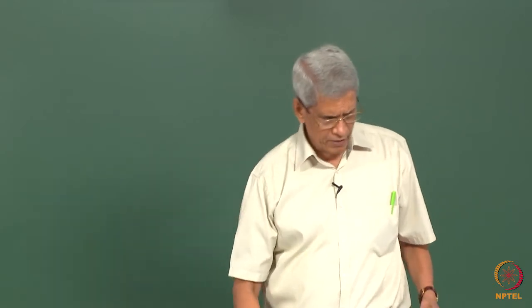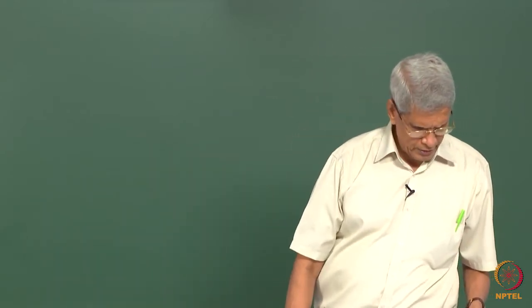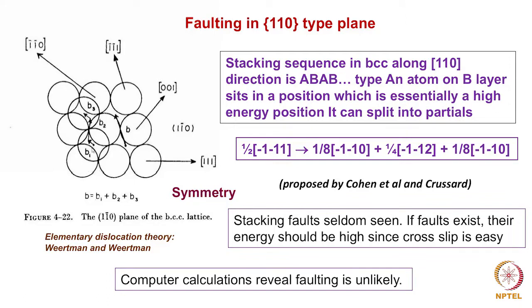Here essentially what we are trying to do is look at how the atom which is sitting on the top should be moved to an identical position by a movement of a/2 111 dislocation. So the atom sitting on the top comes to a slightly low energy position. From there it shifts to another low energy position, from there it shifts to a higher energy position. That is how it can reach.